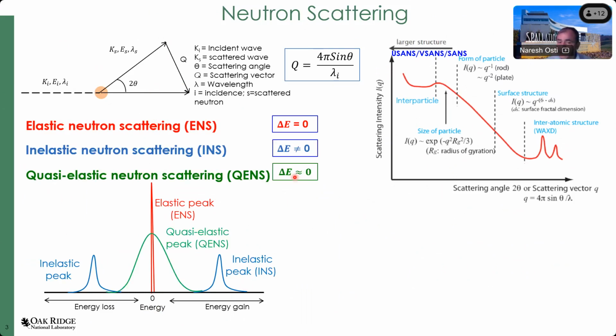There is a third situation where the exchange energy is not zero, but very small. At that time, you end up with a broadening of this elastic peak at the cost of a decrease in the intensity of the elastic peak, which we call the quasi-elastic peak. Depending upon the width of this peak, you can extract the time scale of the dynamic processes happening in the material. And the shape of this quasi-elastic peak gives you some information about the nature of the dynamic processes happening within the system.